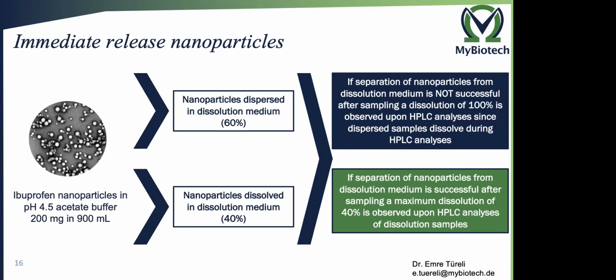So what we would see is, if I have a filtration method which cannot separate the dispersed nanoparticles, which means in my sample which I want to analyze I have dissolved ibuprofen and nanoparticle ibuprofen, then you put it into the HPLC. It is injected into a column. And then you have your mobile phase, for example acetonitrile in your HPLC, which dissolves the undissolved nanoparticles in the sample you injected into the column. And at the end, you have a 100% dissolution profile. But if the separation of the nanoparticles is successful, we should only see 40% dissolution of these nanoparticles.